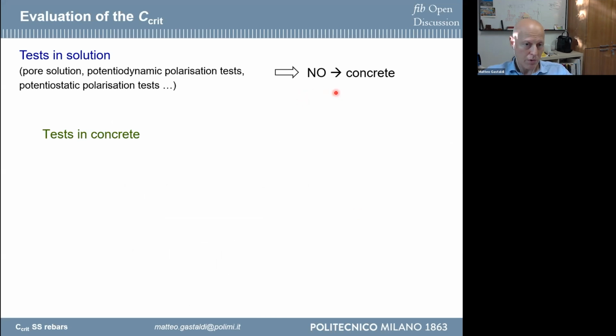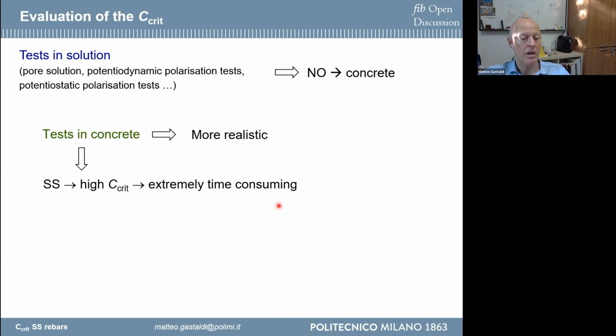So it's not possible to have an idea about the critical chloride threshold in solution, and so we have to move to concrete. What's the problem? The problem is that you need a long time to have the initiation of corrosion in concrete when you have stainless steel, because stainless steel has a high corrosion resistance. For this reason, you need a very long time to reach the amount of chloride that is enough to create corrosion initiation on this steel. And if you make ponding tests, as we observed in the previous presentation, it's not so easy to obtain the amount of chloride at the steel surface, even after 2 or 3 years of testing, in order to have the corrosion initiation.